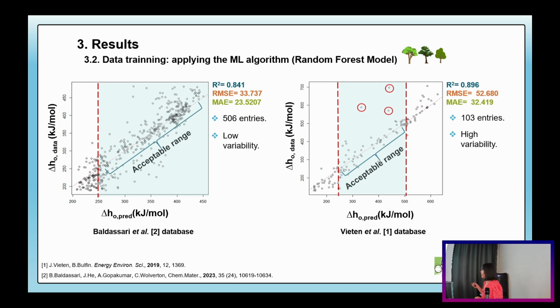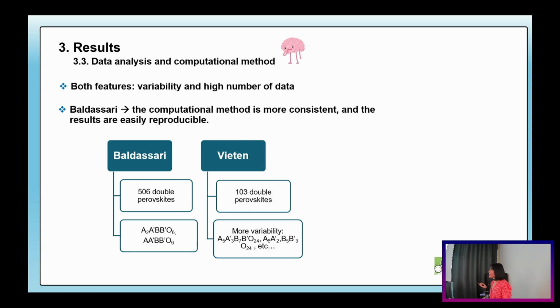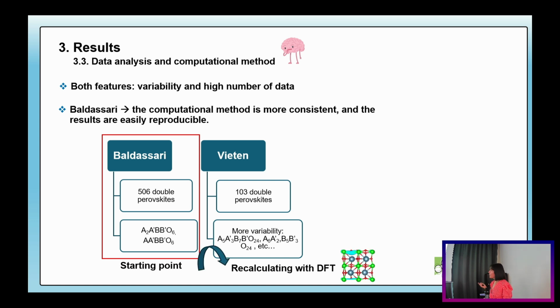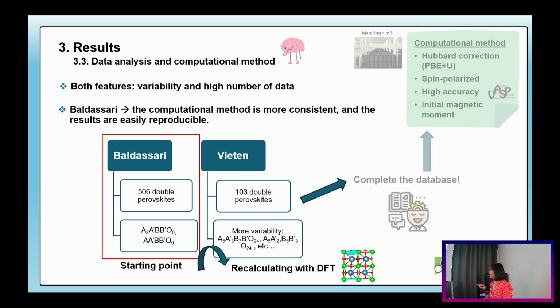But it's true that we also have a higher value of absolute error because the number of entries in this database is less than in this one. So at higher values of oxygen vacancy enthalpy, the prediction is worse. And analyzing this, we thought, okay, we want both features in the database. We want variability and high number of data. So taking into account that the Baldassari computational method is more consistent and her results are easily reproducible, our starting point has been this. So to complete the database, we are recalculating the double perovskite proposed by Vieten using a computational method similar to Baldassari.